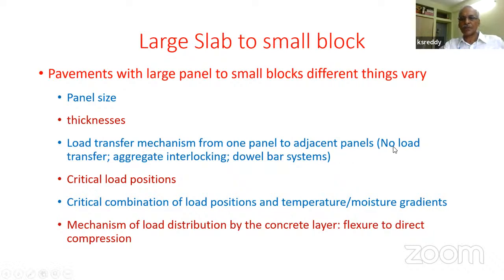In some cases there may not be any load transfer because the blocks have no physical connection. There could be aggregate interlocking. We might put dowel bars connecting adjacent blocks or adjacent panels to transfer loads. And depending on the size of the panel, the critical load positions will be different. So what is relevant in the case of a large panel, which would produce top-down cracking and bottom-up cracking, will be entirely different as you go on varying the panel size. If it is a 2 meter panel, there would be different critical load positions. If it is a 1 meter panel size, different load positions are going to be critical.